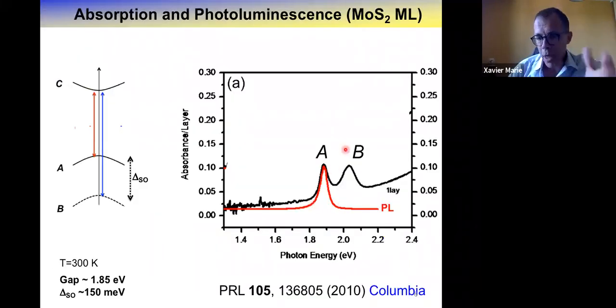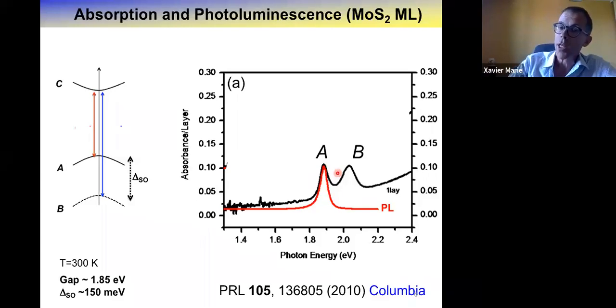Just again, from the beginning, if you are not familiar with optical spectroscopy, you can start with a very basic experiment to get information on the band structure. You can measure, as was done 10 years ago, the absorption of the monolayer as a function of the energy of the photon. And you clearly see in the black curve two very clear resonances on the monolayer, which basically correspond to the transition between the top valence band and the conduction band and the second valence band and the conduction band. So from this splitting, you can get information about the spin orbit splitting in the valence band, about 150 millielectron volt.